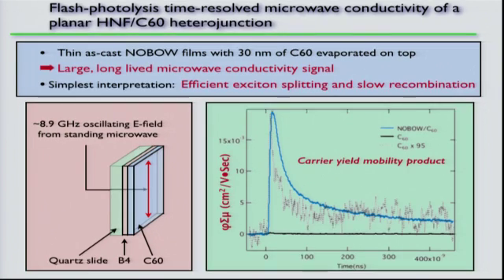You do Gary Rumbles' time-resolved microwave conductivity experiment, TRMC. He's at the National Renewable Energy Lab in Golden, and it's close to us, and we shared a grad student. And what you see is that you flash the PCBM, the C60 stuff. Well, this is actually a thin layer of C60 on top of the helical nanofilament phase, and you generate excitons in the C60.